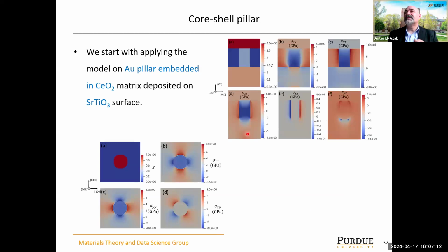FFT works for periodic domains, basically. So we had to artificially add a material, a soft material at the top here, in order to make this domain available for FFT solutions. So it takes a little bit of experimentation with defining this very soft medium on top of the film to get the right stress. So it takes a lot of benchmarking with known solutions and so on.